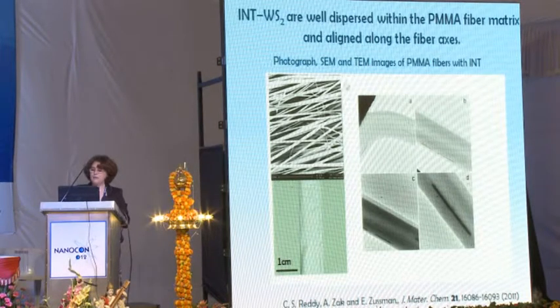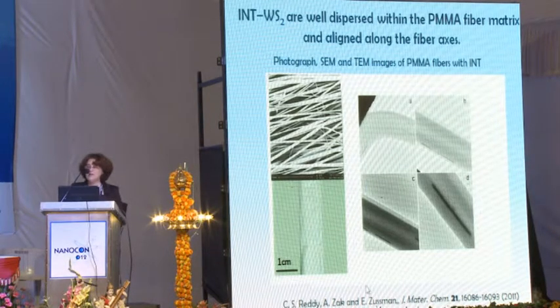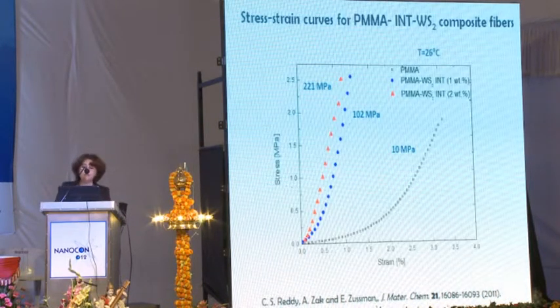This work was already published and was done together with the group of Professor Eyal Zussman from the Technion. You already heard this name today, the institution in Israel, and we prepared these beautiful fibers. It looks like a small mesh, very soft and thin, like you see here, and in the SEM microscope at high resolution you can see how it looks. And you can see the nanotubes, small lines inside the fiber. Beautiful results were obtained, which show that when you embed nanotubes in these fibers, you influence very much the mechanical properties of this polymer composite.